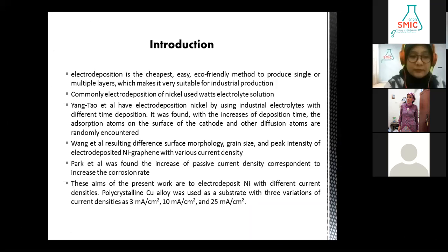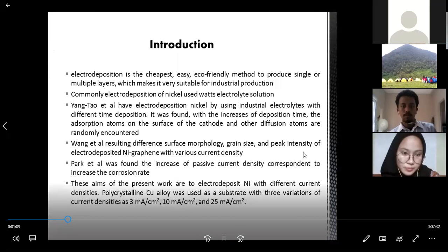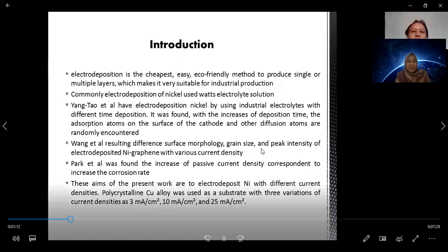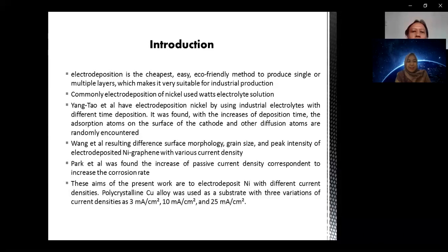Commonly, electrodeposition of nickel uses an electrolyte solution. There are three research works about electrodeposition. Yang Tao et al. electrodeposited nickel using industrial electrolyte with different deposition times. It was found that with the increase of deposition time, the adsorption atoms on the surface of the cathode and other diffusion atoms are randomly encountered. Wang et al. resulted in different surface morphology, grain size, and peak intensity of electrodeposited nickel graphene with various current densities. Park et al. found that the increase of the passive current density corresponds to an increase in the corrosion rate.